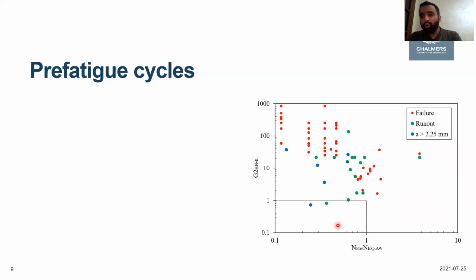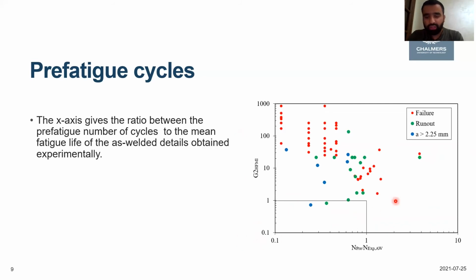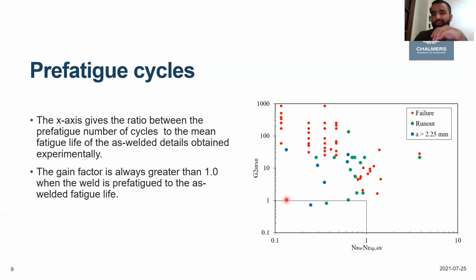So here we include more data points, but now the x-axis is different. Now we don't have the crack size anymore, but we have the ratio between the number of cycles the structure has been tested to before fatigue crack repair using HFMI treatment, divided by the experimental fatigue life of the as-welded detail. When this ratio reaches 1, the experimental as-welded life has been reached. And we see that the gain factor is always greater than 1, even when this ratio reaches 1, which is very promising: we can get fatigue life extension even when the structure reaches its real fatigue life.